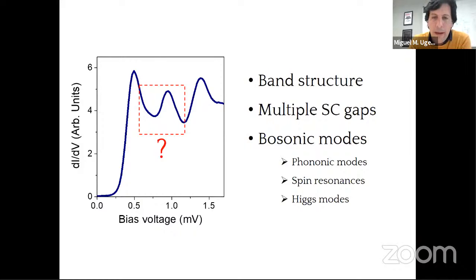So what's the origin of these features? One may argue that these features in the STS, in the density of states, may come from the band structure, but that's quite difficult to believe. We don't believe that this is reflecting any feature in the band structure because, as I said before, in particular within this energy range, there should be nothing in the band structure. There are two pockets, and we don't expect any particular feature.